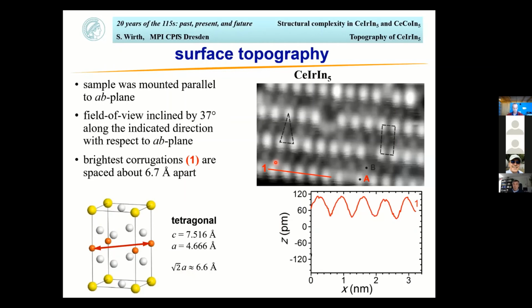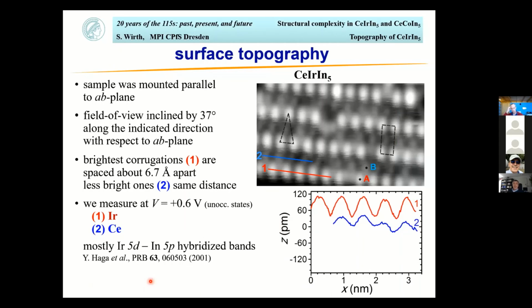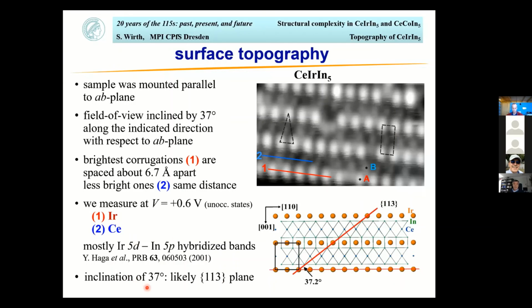Also, if you look very carefully, you see here there is some less bright corrugation. If you zoom into here and take a height scan, it's not as high, but the distances are actually the same. So we think this one here could be the iridium, and this one here the cerium, which we are seeing. That's supported by the fact that we have applied a positive bias voltage. So we look at the unoccupied states, and according to these band structure calculations by Haga et al., at 0.6 volts we see mostly iridium, indium hybridized bands. So with this, we see the 113 plane here. Now, what does it mean for us?